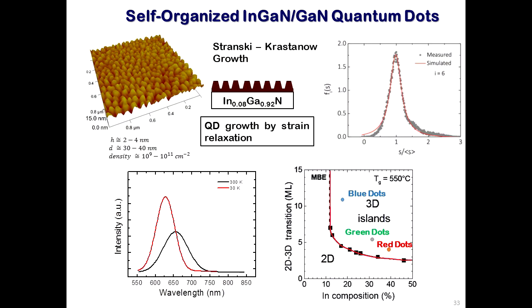So this is what the self-organized quantum dots look like. They are typically about 2 to 4 nanometers in height. This is an atomic force microscopy image. We can vary their density all the way from 10^8 to 10^11 per centimeter squared, and we've done all kinds. So they are kinetically driven, and this is a kinetically driven model. This is a scaling function for the height of the dots, and it obeys a scaling law.